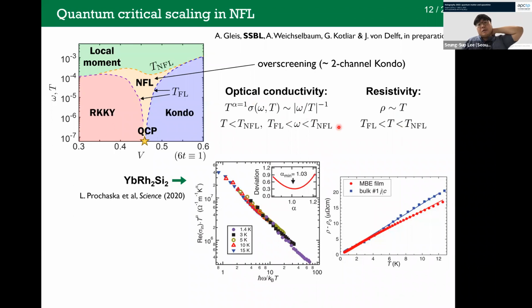And actually these results are very consistent with recent experiment on the same material. So they found the scaling collapse of optical conductivity by playing around with the exponent, and they found that the exponent for this optimal scaling collapse is 1.03, and what we have found is one, it's very close. And also they have found the linear in T resistivity, which is the characteristic of the non-Fermi liquid or strange metal. And we could explain that this behavior comes from the overscreening along two-channel Kondo effect.